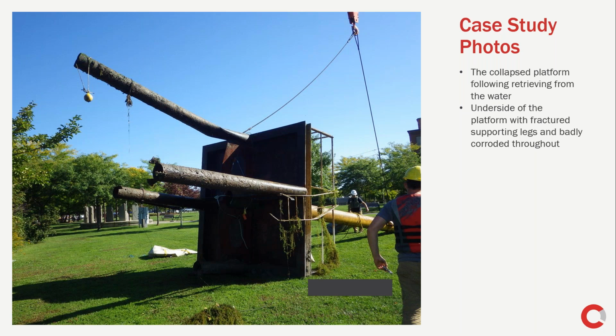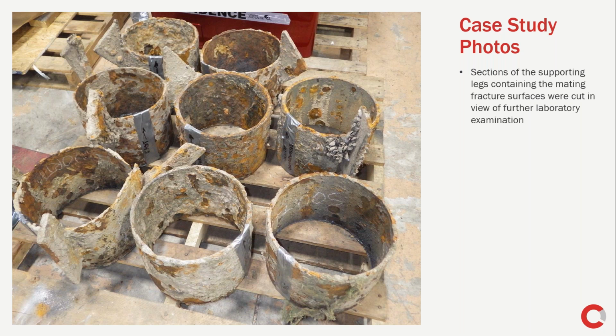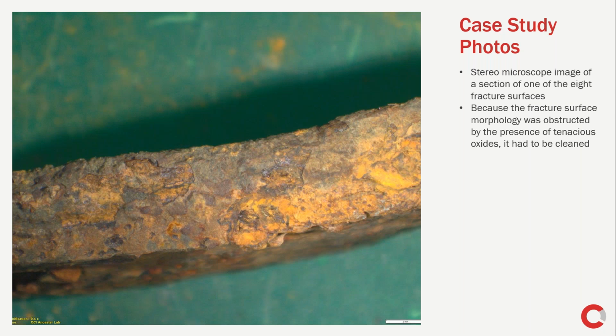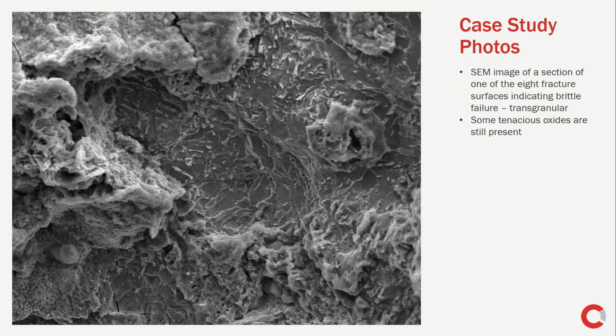It was a difficult task to look at the fracture surface because of severe oxidation and degradation. We cut small sections from the legs and we tried to determine what could happen to the platform that it collapsed. Cleaning was very tedious because, as I said, of the extensive damage to the fracture surface. We used special chemicals and we managed to look at the fracture surface. This is the appearance of the small sections of the fracture surface before being cleaned. After ultrasonic cleaning, we took the samples to be examined under a powerful microscope called a scanning electron microscope. This microscope allows us to examine fracture surface and features at higher magnification.